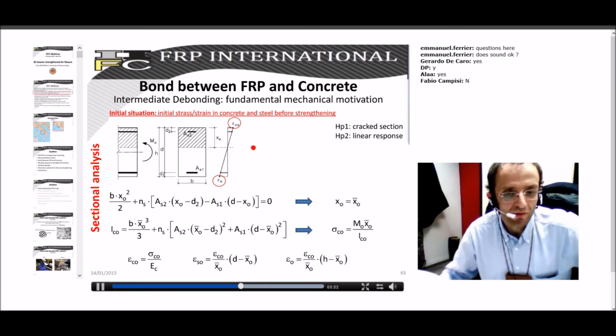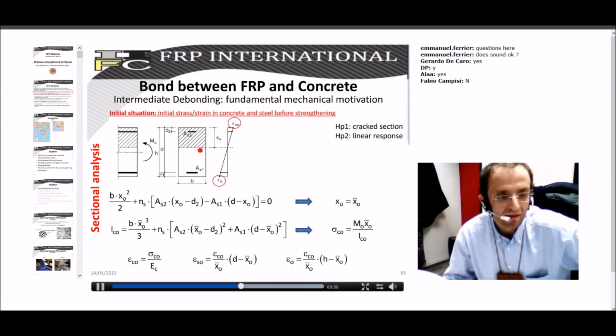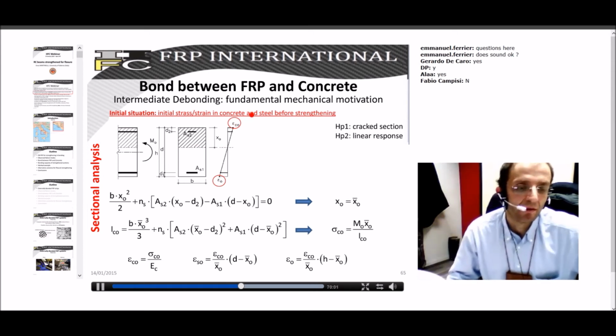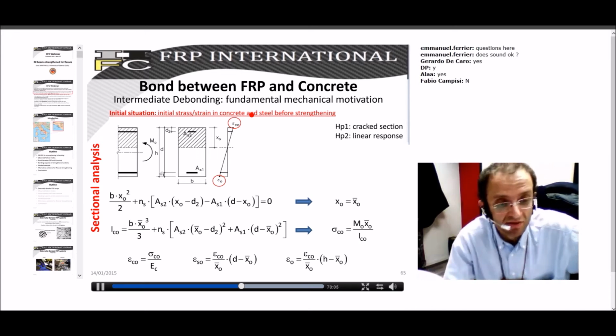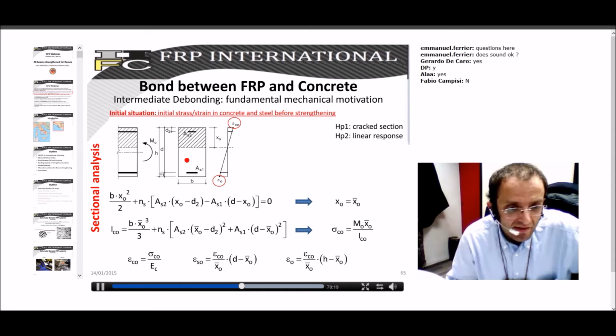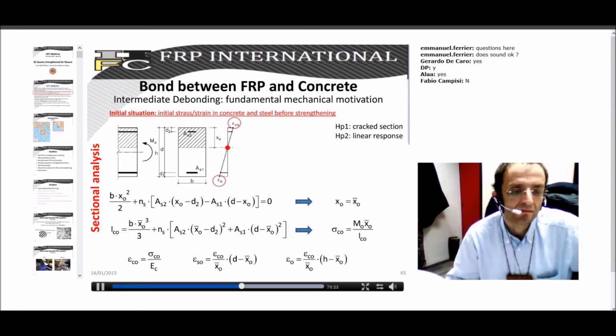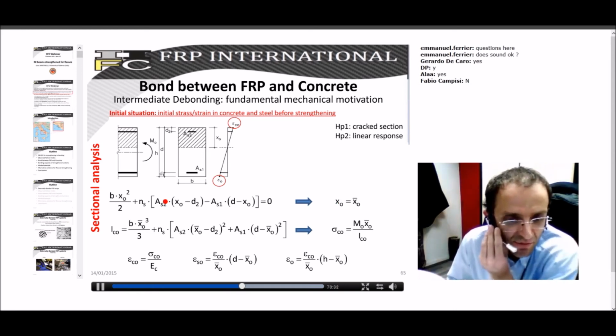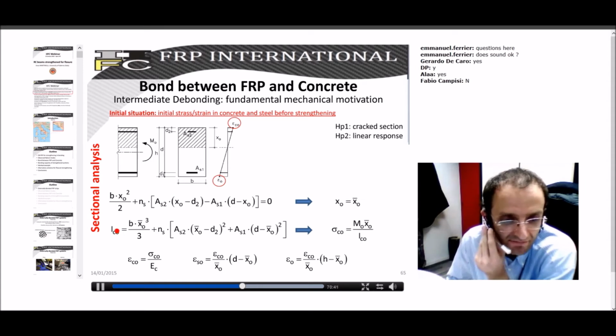This is something already known for RC sections. For instance, if you want to evaluate the stress state of materials before strengthening, you have to consider all the loads applied before strengthening. So self-weight for sure, some sustained loads if they are present before or during the application of the FRP strip, and then you can, for instance, assume a linear cracked situation for your section, and then you can evaluate the position of the neutral axis in bending as usual by finding the zero value of the static moment of the resisting section, and then you can evaluate the moment of inertia and evaluate, according to the Navier formula, the sigma zero and the corresponding epsilon at the top and of course at the bottom, because this is important.